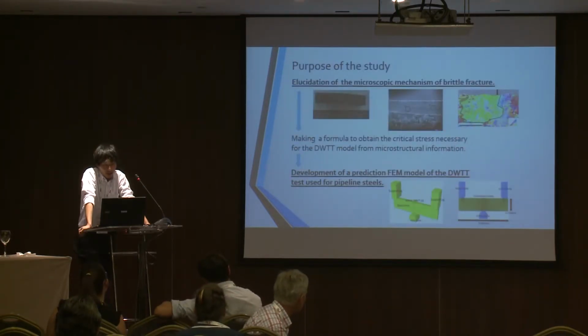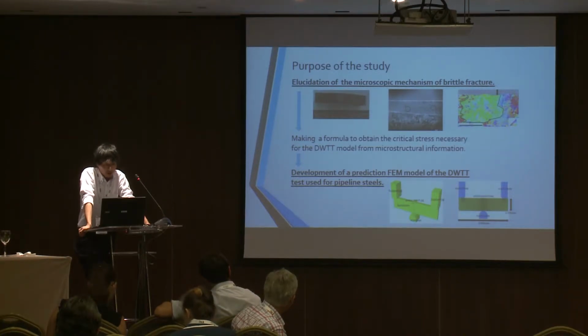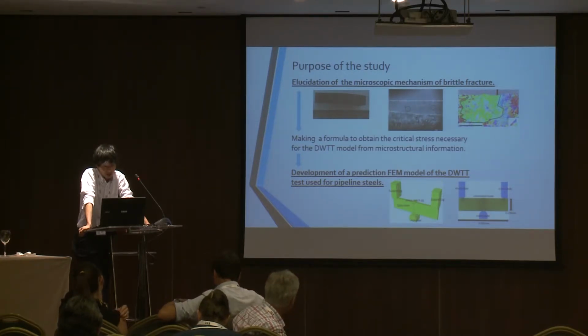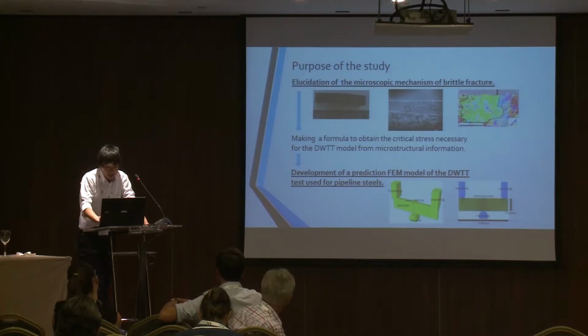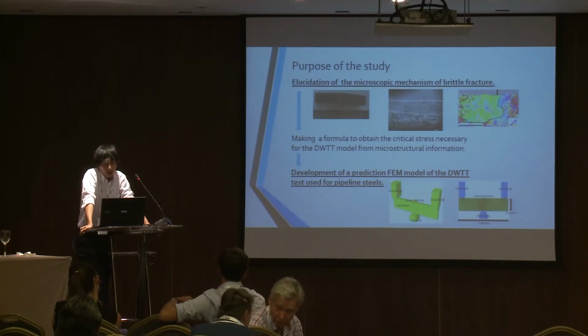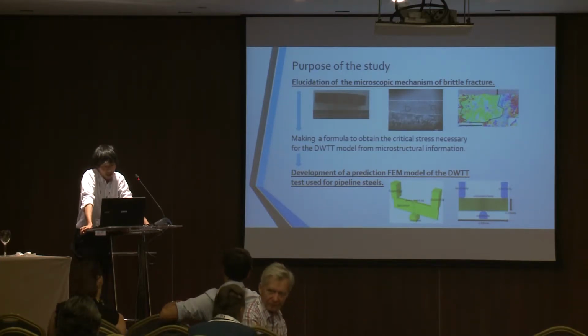The purpose of the study is as follows. First, elucidating the microscopic mechanism of brittle fracture. Second, making a formula to obtain the critical stress necessary for the DWTT model from microstructure information. Finally, developing a prediction FEM model of DWTT test used for pipeline steels. The DWTT test is a standard test to examine pipeline performance. If we can predict this test result from the microstructure, it will contribute greatly to the development of new material of high strength and toughness.